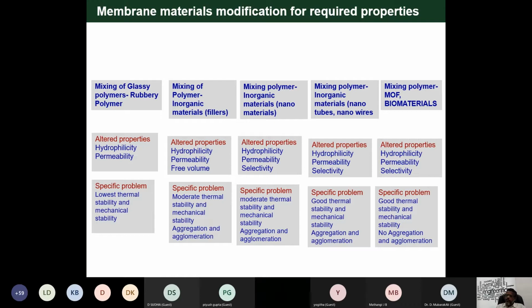It's very difficult to make ceramic membranes because they are brittle and rigid in nature. Polymer has thin film property and is easy to fabricate initially. Then what did we decide? We coat polymer material on a ceramic substrate. So we coated polysulfone on the ceramic materials. But there are some difficulties. There needs to be some compatibility between the ceramic materials and polymer materials. If there is suitable compatibility between the two materials, you can fabricate that kind of material.